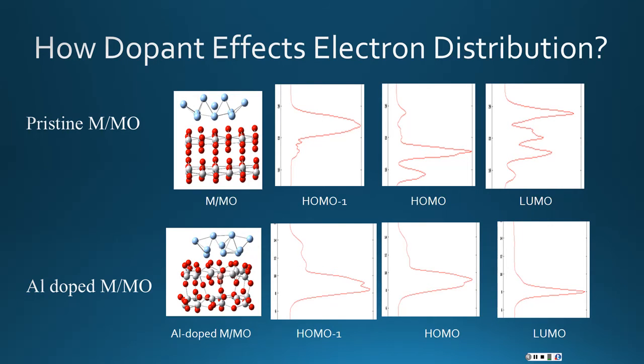This one is giving us a 2D presentation of the orbitals, showing how the electron is localized, in which part, in which layer, metal oxide layer or metal layer. This one is showing the pristine one, and this one is showing the aluminum-doped one. If you look at this lattice structure, by doping aluminum the lattice structure is distorted much, but this one almost shows the pristine titanium oxide lattice structure. In this case, in HOMO-1 and HOMO, there was some electron delocalization on the metal part, and in the LUMO too. But when I dope aluminum, this electron is moved towards the oxide part, and the LUMO also shows all the electron transfer. So maybe because of this oxygen, it could introduce a charge transfer here.